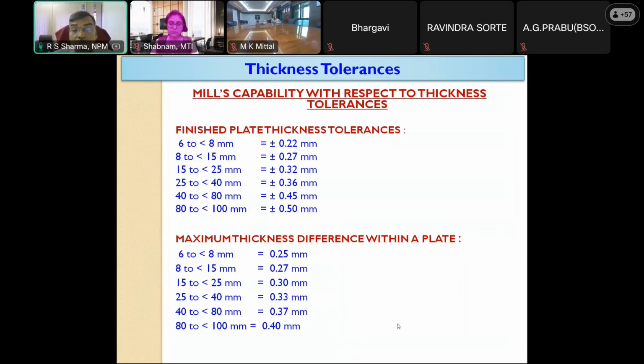And then somebody may ask what will be the maximum thickness difference that this mill can supply within a plate, because the earlier table was for a thickness range, for 8 mm, what is the range. But within a plate, the maximum thickness range is again graded thickness group wise, and it is mentioned as 0.25 for 6 to 8, 8 to 15, 0.27, 15 to 25, 0.30, 25 to 40, 0.33, and 40 to 80, 0.37, 80 to 100, 0.40.